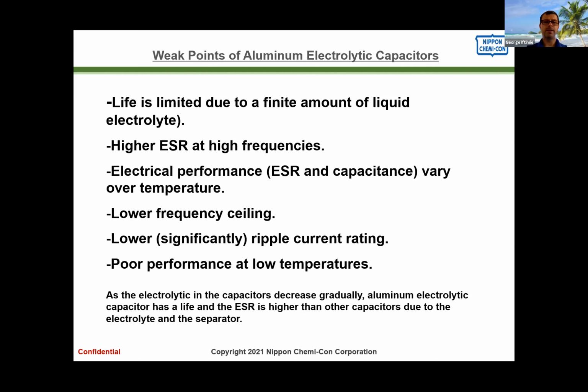I mentioned earlier about the electrolyte. The electrolyte's viscosity changes with temperature. And as the temperature decreases, the electrolyte gets thicker and its resistance increases, which translates into higher ESR and lower capacitance. You tend to have a lower frequency ceiling compared to a polymer and a hybrid. That's basically the self-resonant frequency tends to be lower than the other types of products.